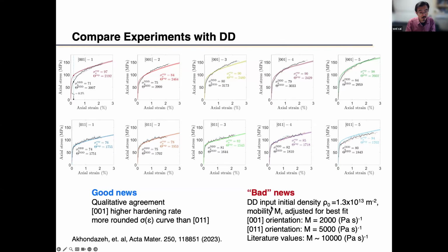And furthermore, for the 001 orientation, we have to use an even smaller mobility than for the 011 orientation. So that is kind of the biggest problem in some sense, the biggest defect, if you want, or criticism you can raise for this work: the mobility. But other than that, every other parameter that we use for the simulation is the same, okay? They are the same simulation parameters for all of them. Because if you adjust each individual parameter, then we can have a perfect fit for every curve, right? So other than this adjustment for the mobility, there's a unique parameter set for all the simulations, okay?